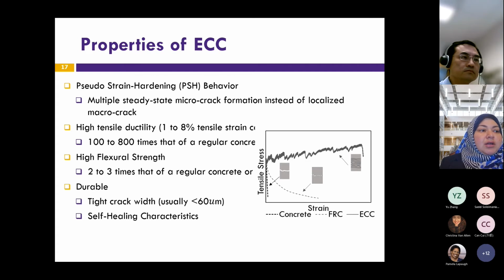Okay, so what is pseudostrain hardening? Pseudostrain hardening is a behavior that allows the material to exhibit microcracks. You can see here, there are so many cracks instead of just one, right? When we look at concrete cracking, we have one. Even fiber reinforced cracking, we still have one, although the reinforcement tries to bridge the gap in the crack, right?